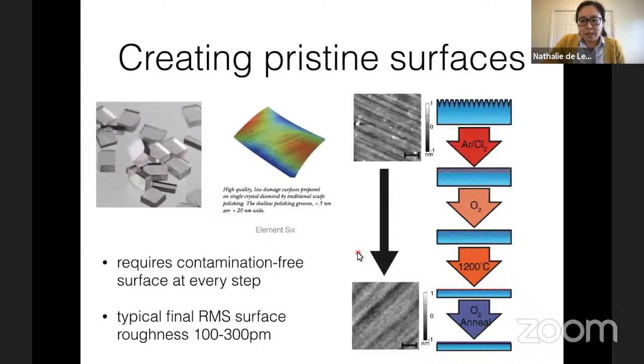So using this kind of feedback tool, we identified that one of the critical pieces is that you really need to maintain this smooth surface morphology while maintaining well-controlled surface chemistry. We came up with a laborious process for creating pristine oxygen terminated surfaces. We start with state-of-the-art polishing that gives you low subsurface damage, and then these very shallow polishing grooves and sub-nanometer surface roughness. But that leaves behind a large amount of subsurface damage that gives you very highly strained layers. So you need to remove that by reactive ion etching.